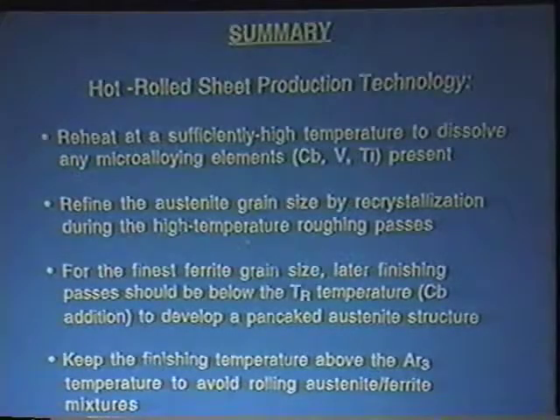So a summary of this really dry metallurgy: we have to reheat at a sufficiently high temperature to dissolve the microalloying elements, be it columbium, vanadium, or titanium, or alloy of your choice, and that's 2300 degrees. We refine the austenite grain size, that non-magnetic stuff, by recrystallizing during the high temperature roughing passes. Recrystallization, that's the redoing of the grain structure, letting it relax again after it's been worked. For the finest ferrite grain size, you want the smallest grain size you can get, the biggest bang for your buck. The later finishing passes should be below the recrystallization temperature to develop a pancake austenite structure.